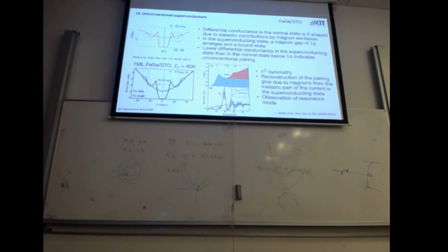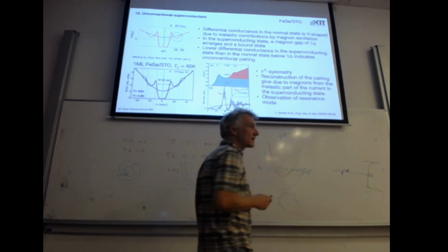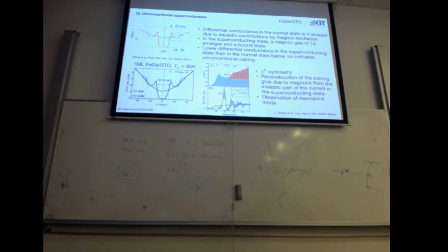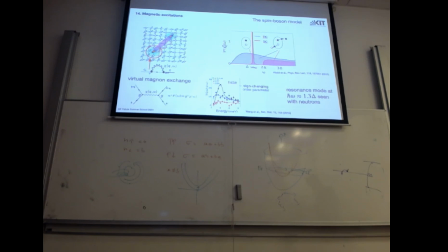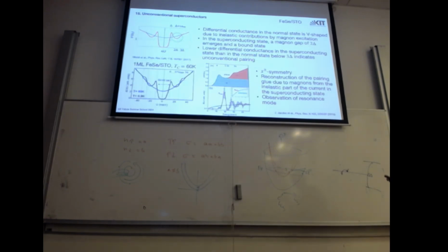How reliable is this data evaluation? It seems to be a very complicated procedure. Yes, it is a problem because our data is noisy. It's an ill-posed problem. So you cannot strictly deconvolute, but we take a test bosonic spectrum, calculate how our tunneling curve will look like, and then vary it and minimize the error. So if this is the unique answer, I can't tell you, most likely it's not unique. But we get at least this very strong peak. And this resonance mode here, for some reason, lies at 1.3 delta, and this is also where we find it. So it's at 1.3 delta.